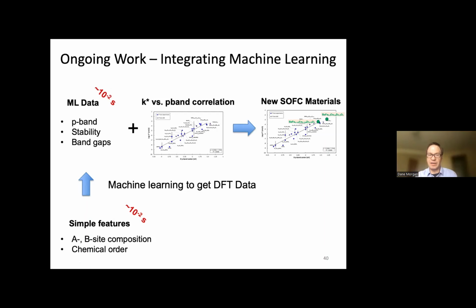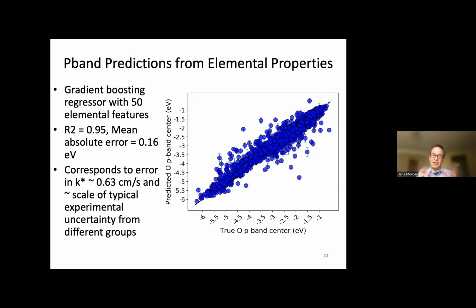So I'll give you one concrete example of doing this with the p-band part of the data. This is our machine learning of p-bands. We took all 2,000 calculations we had done. We used a technique called gradient boosting, where we correlated the p-bands we had calculated with features of the elements we had used, things like their melting temperature, their bulk moduli, their densities, properties of the elements. And we were able to predict back a new p-band that we hadn't looked at before with a quite good accuracy.